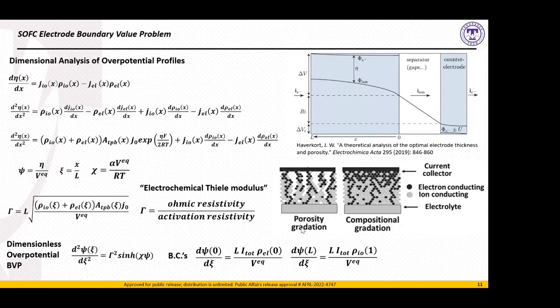This does correct some previous errors that exist within the literature. Some other groups have studied functionally graded electrodes, but oftentimes when they took this second derivative here, they failed to account for the fact that the resistivity and the porosity, therefore the gas diffusion, could change throughout the electrode. So this has to be approached as a coupled problem.